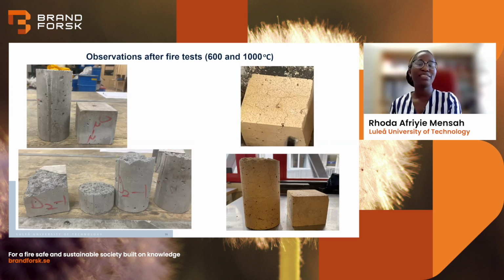After the fire test, we made some observations. At 200 degrees Celsius, no visible changes were seen, but at 600 and at 1,000 degrees Celsius, we noticed significant thermal cracking and color changes. The thermal cracking could be a result of water evaporation, which caused the cement to lose its binding ability. And the color change was due to the iron in the aggregates oxidizing, which changed the color from grayish to brownish.